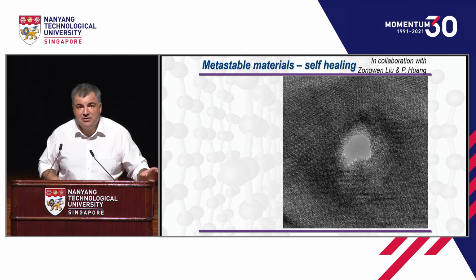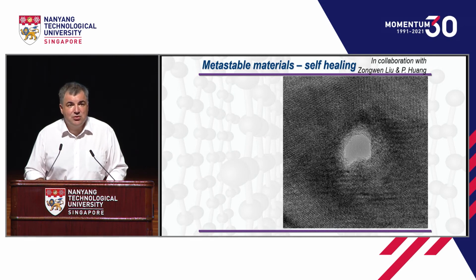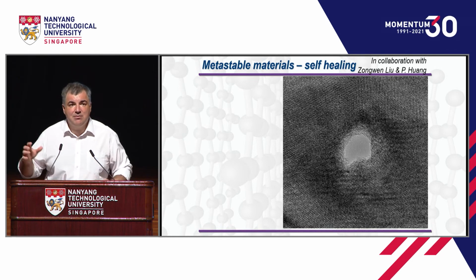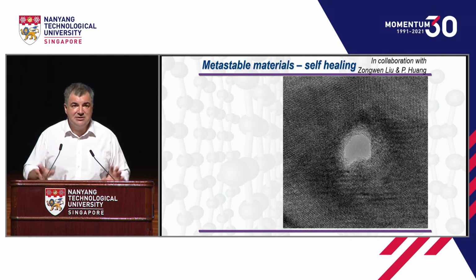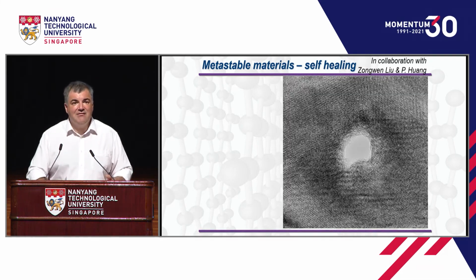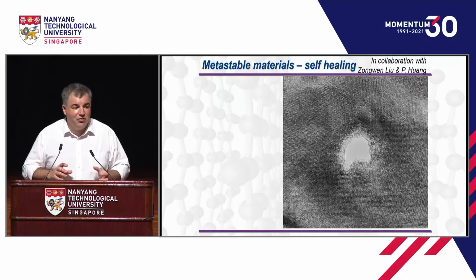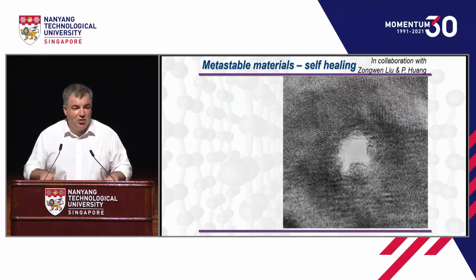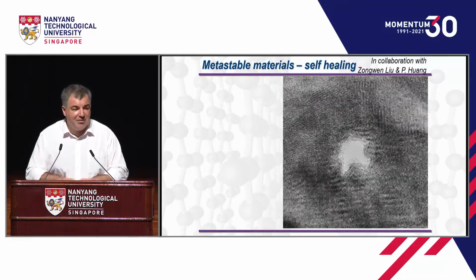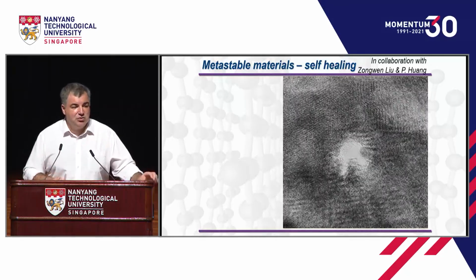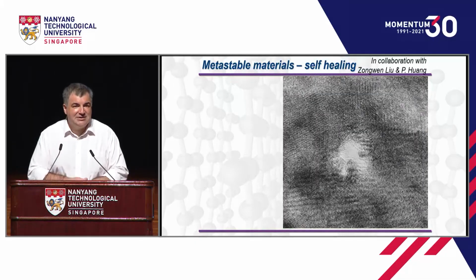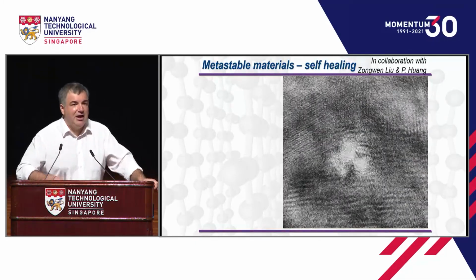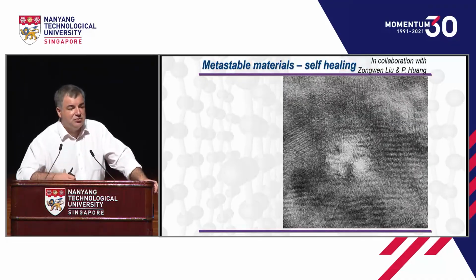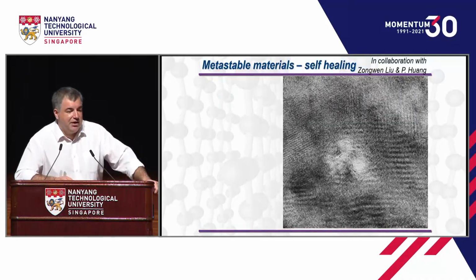Here we program a self-healing mechanism into our crystal, a high entropy alloy. At high temperature, where you grow it, it is in a metastable state because it's stabilized by the huge entropy, as we combine many different elements. But then at low temperature, where you use it, if you make a hole, you have enough energy from the surroundings of this crystal to heal the hole and close it up, and after just a few minutes the crystal repairs itself, just like any living system. So we're basically redirecting the entropy into the enthalpy depending on the external conditions.